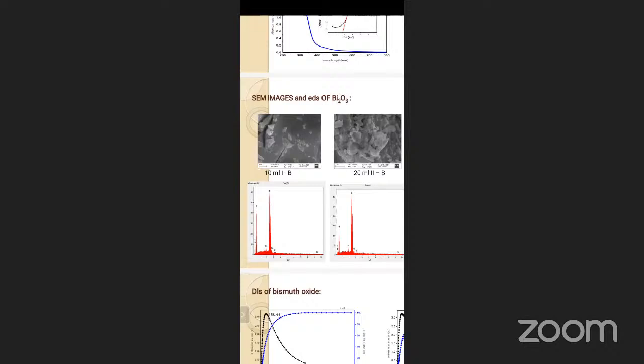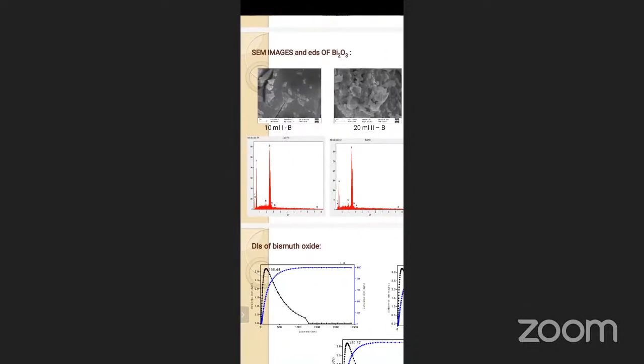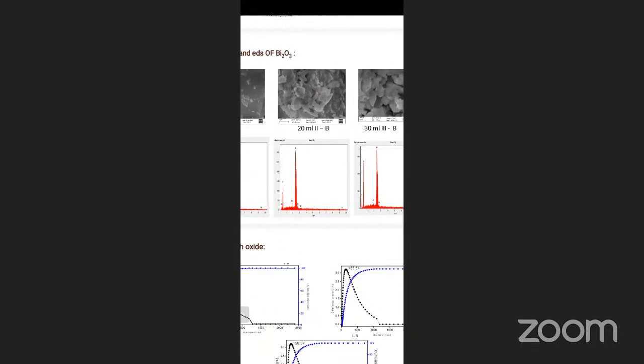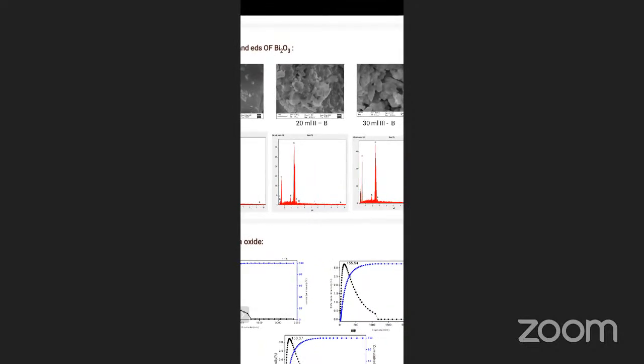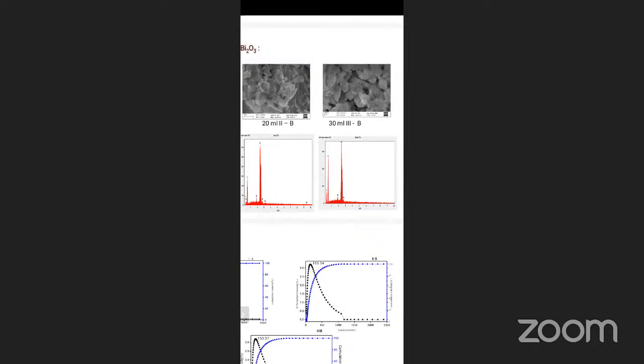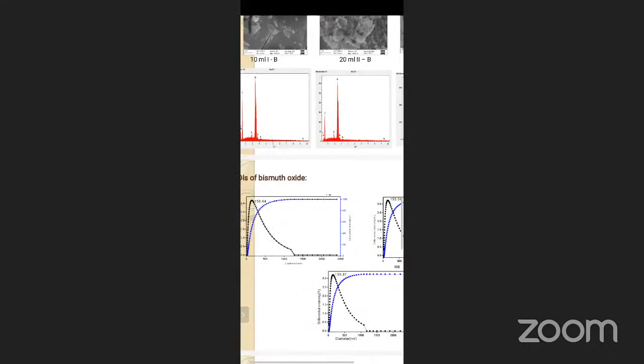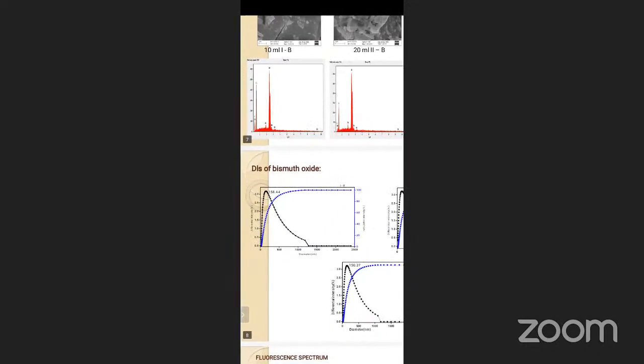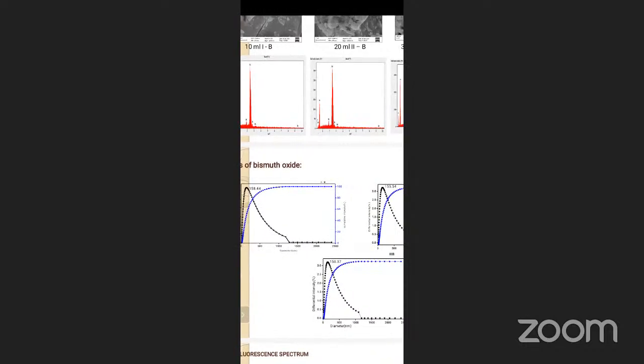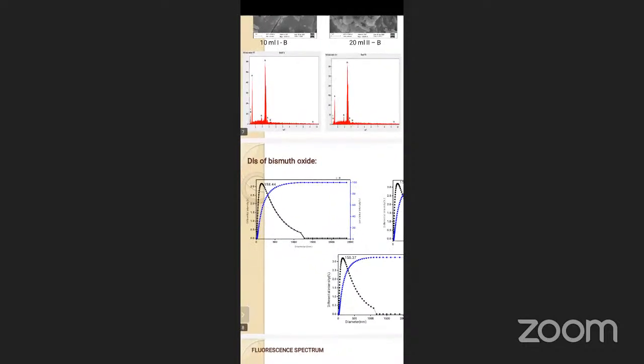Here, for the first sample we get a sheet-like structure, and the bismuth peak is high due to the formation of different phases. Bismuth oxide has five different polymorphs: alpha, beta, gamma, delta, and omega. In this we get different phases. For the 20 ml sample, we get some spherical-like structures. In the third sample, we get some agglomeration. In these three samples the bismuth and oxygen values are nearly the same, and the bismuth value is high. With this we confirm that bismuth oxide is formed.